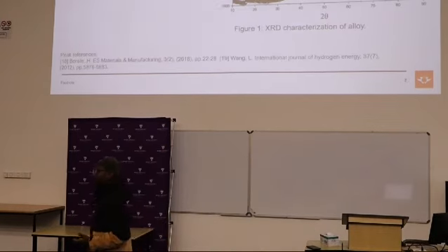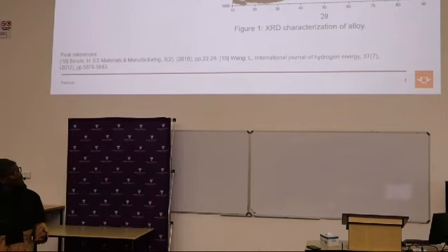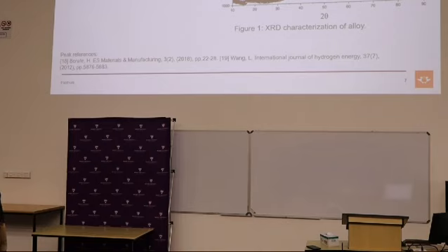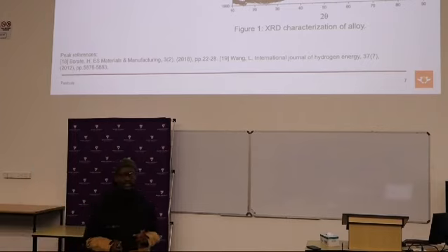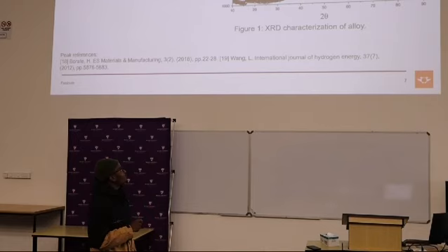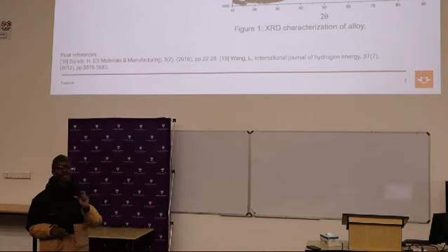Now, let's look at the characterization by X-ray diffraction. We find that in our X-ray diffraction, we've got 4 peaks that were visible. So we've got the 110, 200, 211, and the 220, which are characteristic of a BCC phase structure. But we also find the existence of a phase, which is what I was talking about, the A15 phase.